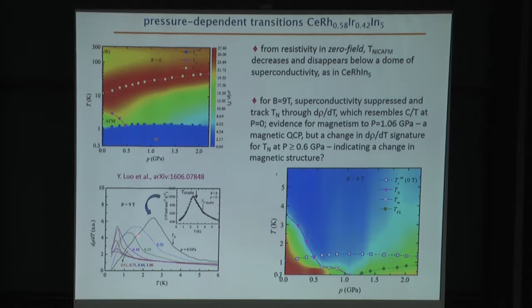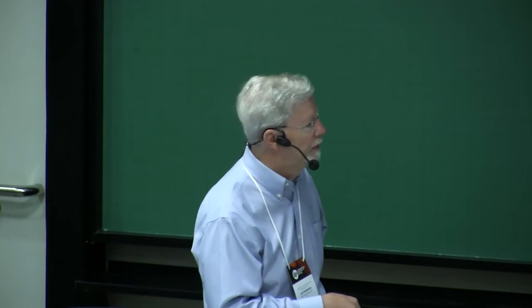So this similarity between the temperature derivative of the resistivity and specific heat allows us to track the magnetism to lower temperatures. And what we can see just by simple inspection is that evidence for magnetism, at least from the peaks of features in this derivative, exists to pressures at least of order 1 GPa or so. So clearly well above where it disappears in zero field.